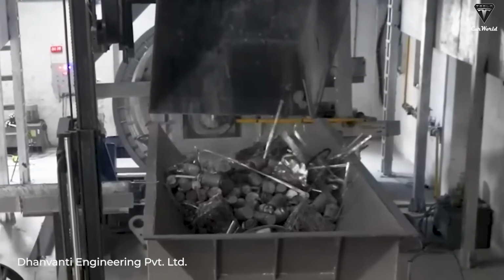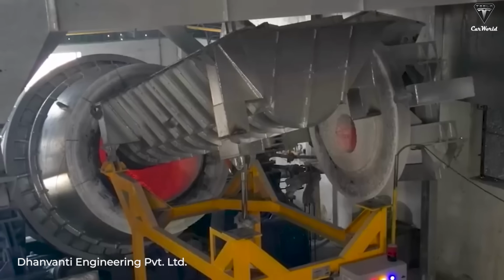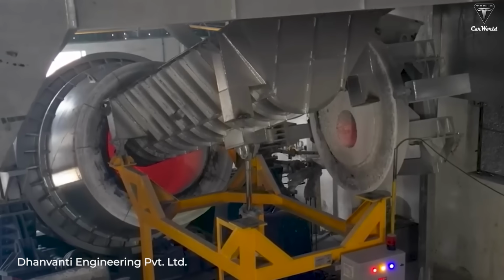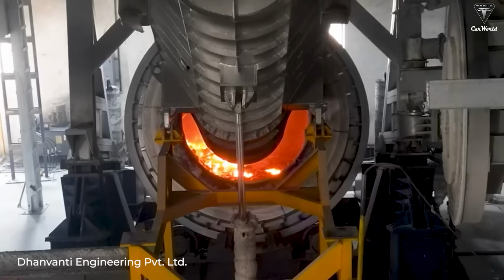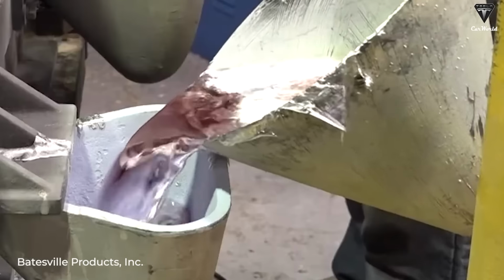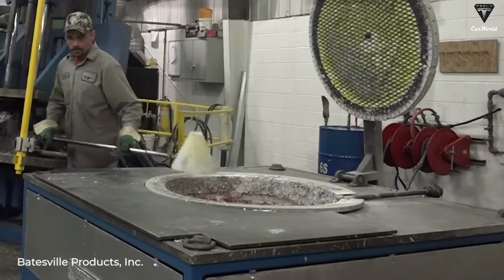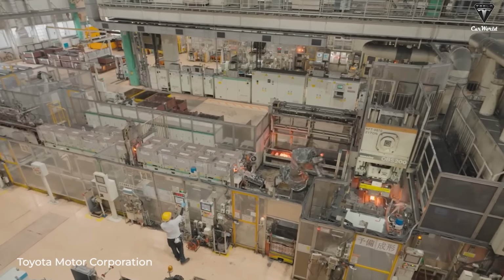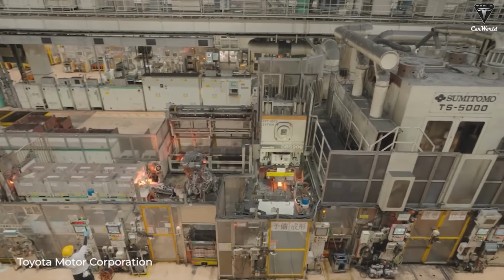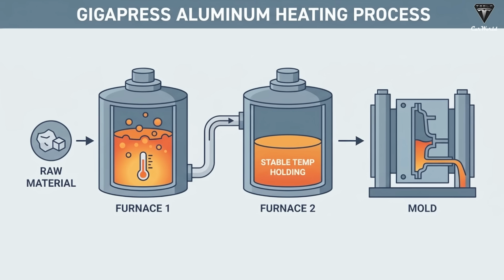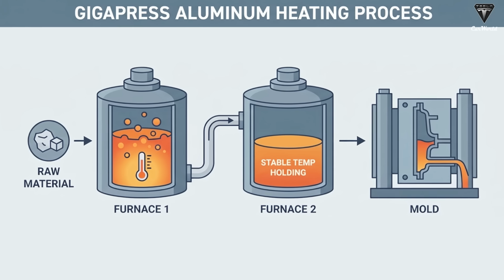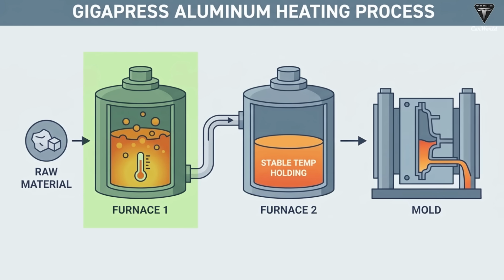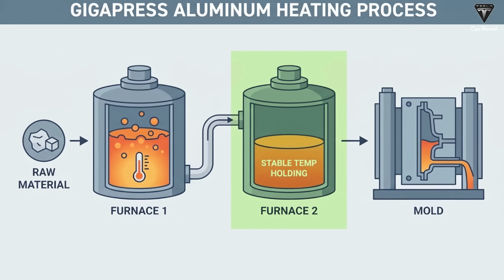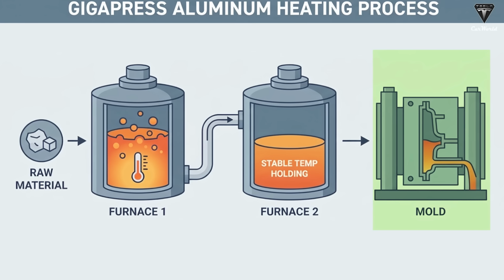Fresh material, along with recycled aluminum from previous casting cycles, can be fed into a furnace and heated to around 850 degrees Celsius or 1,562 degrees Fahrenheit until it becomes molten metal. Once surface impurities are removed, the molten aluminum is transferred into an enclosed holding furnace where the temperature is carefully maintained within the proper range so the metal is always ready for the next injection cycle. Available technical documentation describes a two-furnace system. One furnace is responsible for melting the aluminum, while the second keeps the molten metal at a stable temperature before it is injected into the mold.